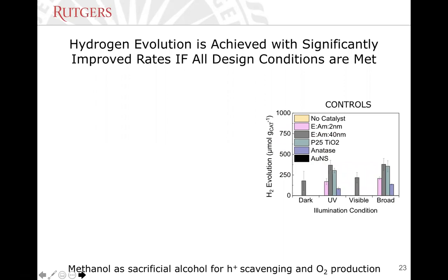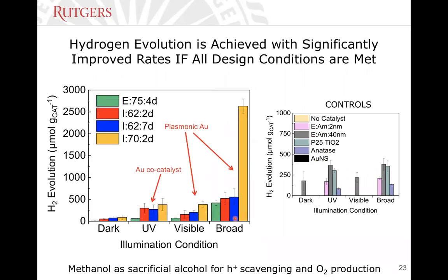So now we tried our optimized nanoparticles, and look at this yellow bar. We increased the production of hydrogen by almost 10 times in the same conditions by using our optimized nanoparticle. This is really exciting because by tuning in very high detail the properties of the nanostars, we can really produce hydrogen from water in situ. So imagine having this scaled up into production and delivered wherever small energy consumption needs are present. That could be very impactful in countries where there's no access to electricity.